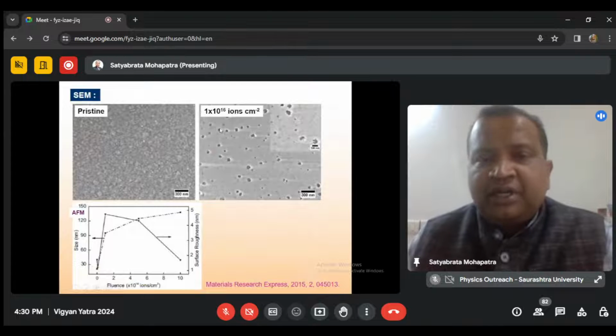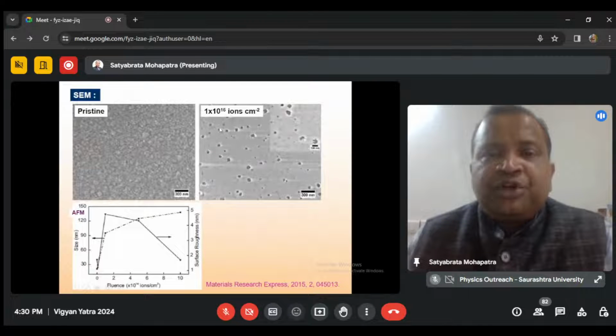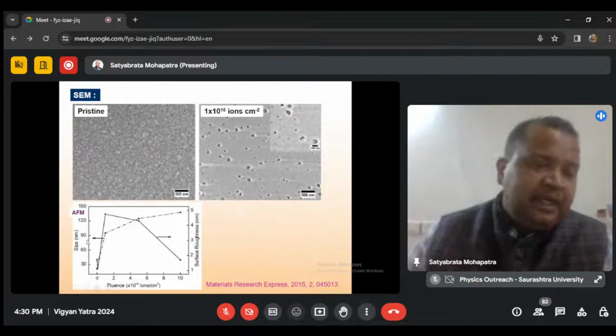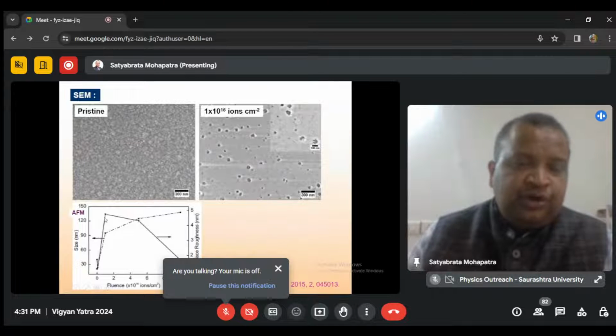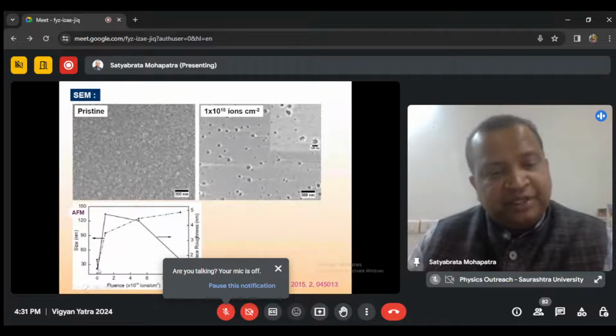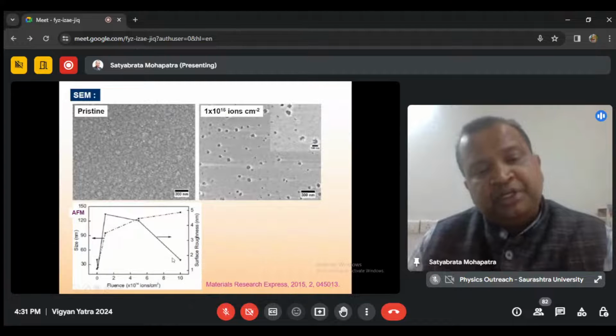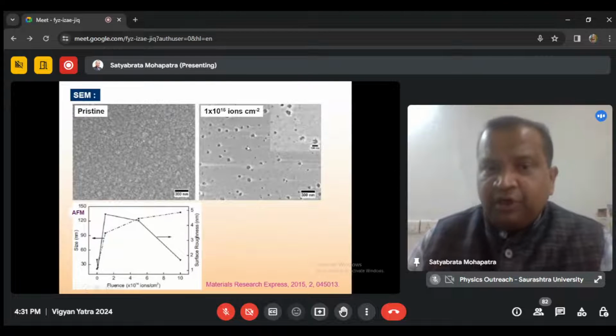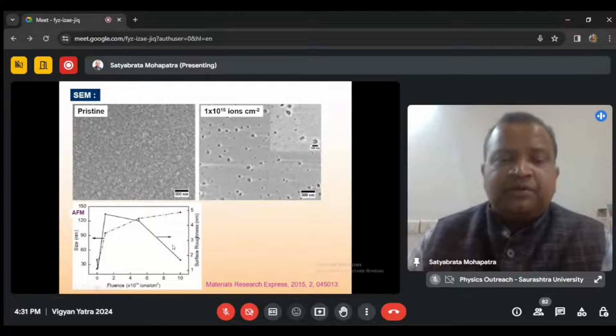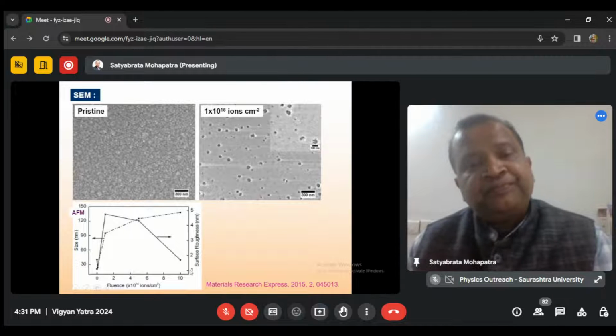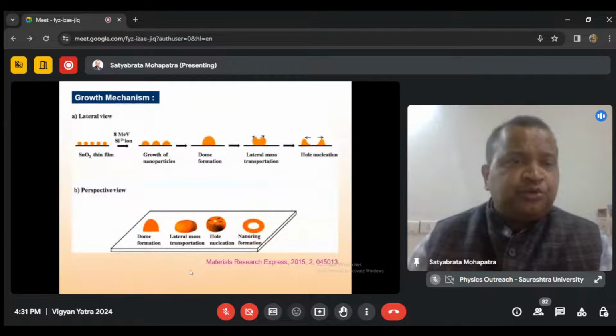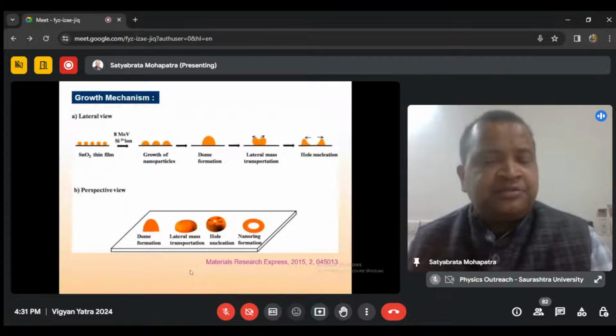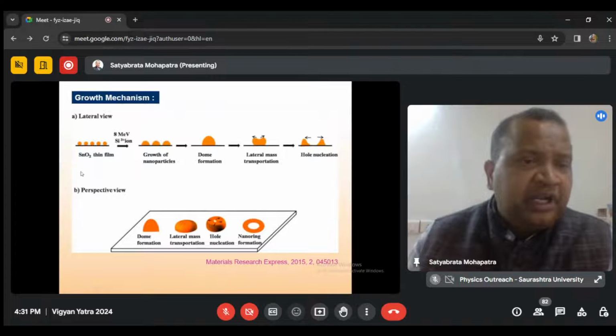You can see that there are these holes surrounded by nanoparticles, and the size of these increased from 21 to 138 nanometer, whereas the surface roughness increased initially up to 4.7 nanometer, then decreased to 1.6 nanometer. So once these rings develop, the surface roughness reduces.